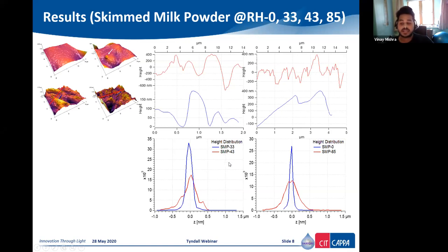when the lactose crystallization had already happened. While comparing the result of skim milk powder at relative humidity zero versus skim milk powder at relative humidity 85, you can again see the narrow height distribution versus the height distribution at relative humidity 85, showing a higher amount of lactose crystals and their mountains.